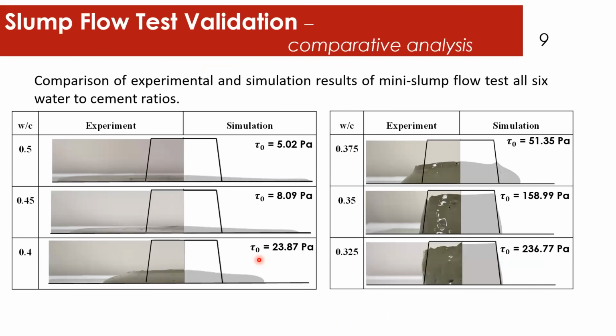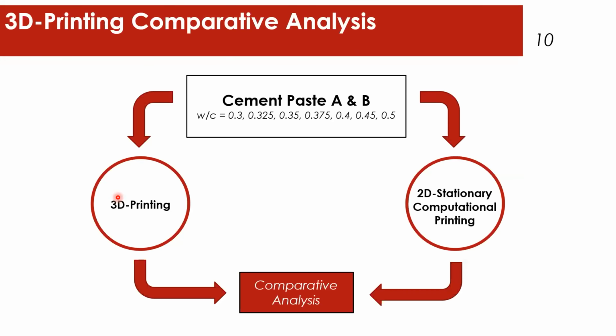So here is the comparison of experimental and simulation results of the mini slump flow test, from 0.325 water to cement ratio all the way up to 0.5, that are in good agreement with the experimental results. Now I need to compare the 3D printed object to see if I can actually predict the morphology of the printed objects instead of the slump cone.